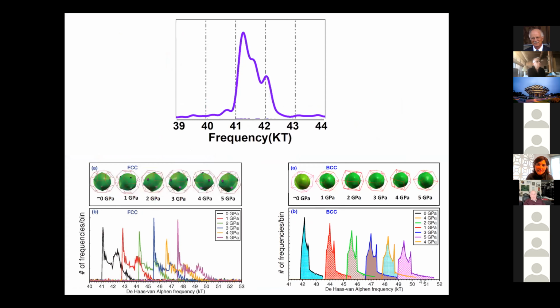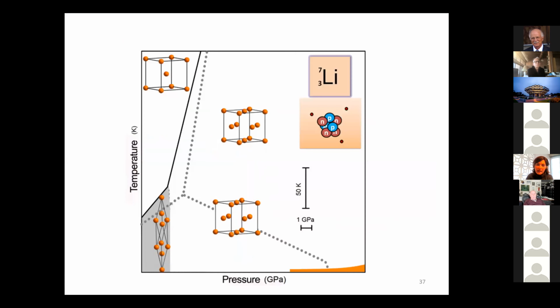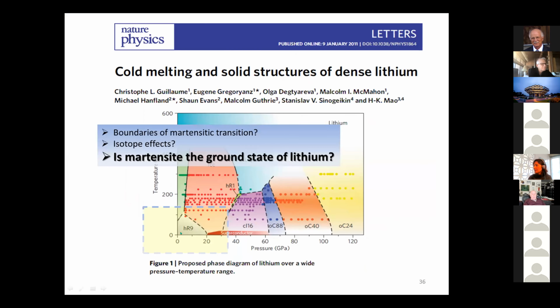My guess is that if you look at something that has such complicated structural phase boundaries, there are going to be more than just this one place where we see the instability, and many of these phases can be metastable, because most of them have been created by isotherm. You kept the temperature the same and you pressed through. And there is where you get a lot of instabilities, lots of metastabilities. That's a recipe for creating metastability, to stay on an isotherm and press.